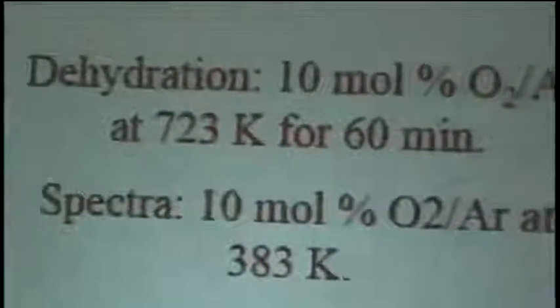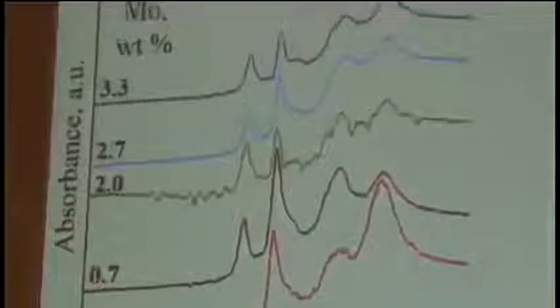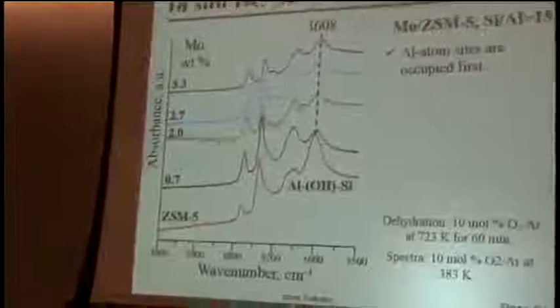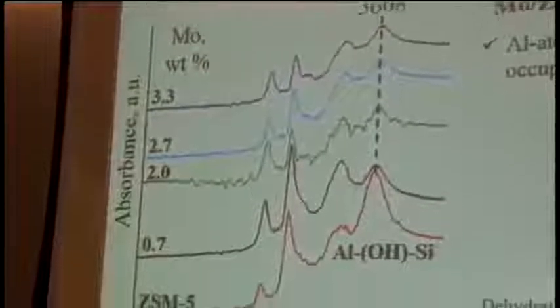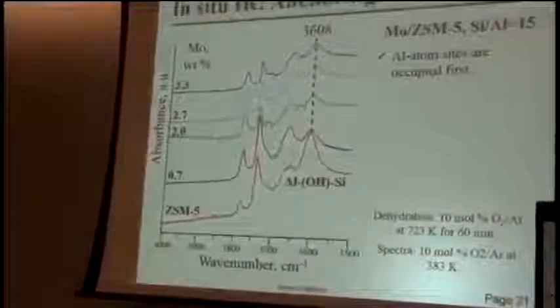We have direct evidence observation of the anchoring sites. If we do the IR measurements, we can see those OH groups before we put the molybdenum on the catalyst. So this is the spectrum at the bottom. As we put the molybdenum, we can see the decrease in the IR peaks for those hydroxyl groups. The OH groups on the aluminum sites, they're all the same, because initially we just have hydrogen. So we do not discriminate with IR between double aluminum and single aluminum, because hydrogen is the same on all of them.